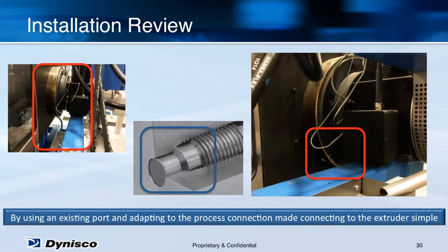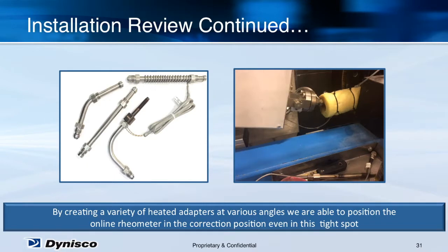The areas that we had to overcome was that the port was located at a negative 15-degree angle from the 9 o'clock position, and as shown in the pictures to the left and right, the real estate that we had to work with was quite tight. While visiting a number of extrusion facilities, we found that most existing ports that we could use were in less than ideal spots. To correct this, we developed a series of heated process adapters that are available to meet a variety of angles. These are designed in such a way that they divert the stream not only in a variety of angles, but the tube itself can also rotate before it's locked down. This adjustability allows us to adapt to most locations without specially designed adapters.